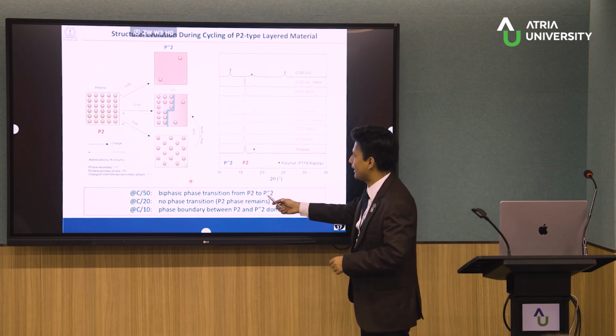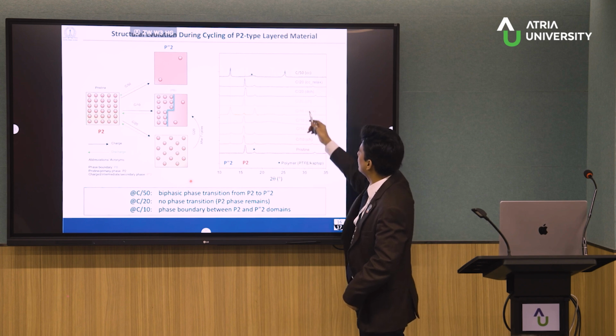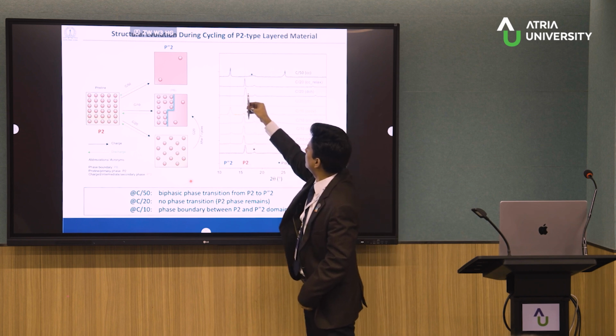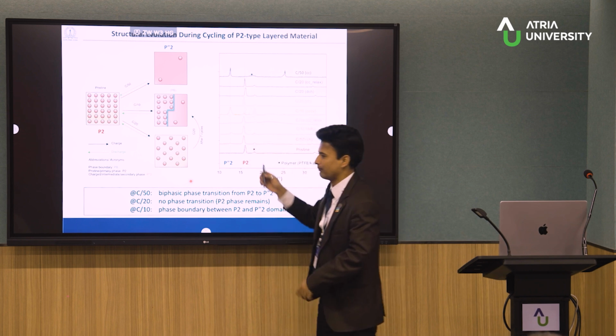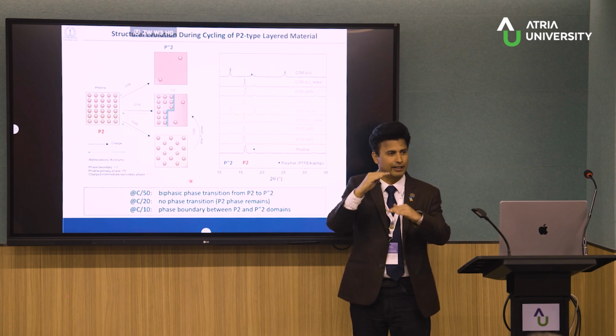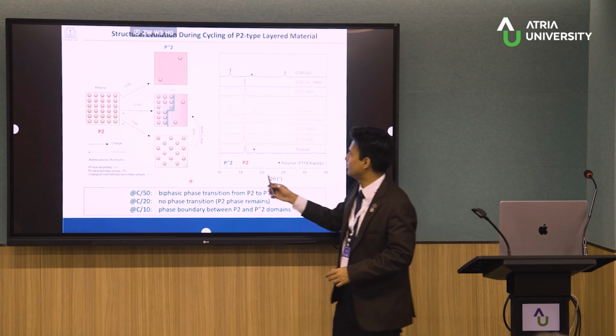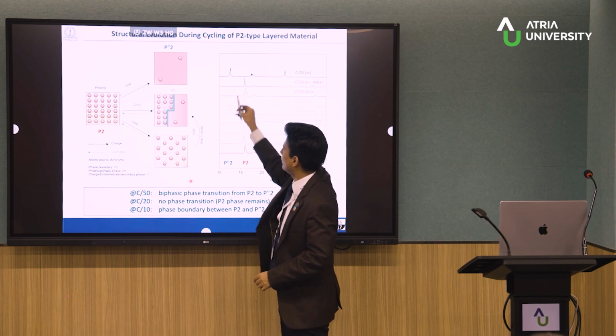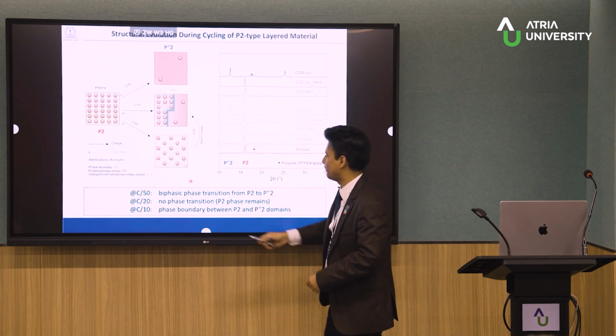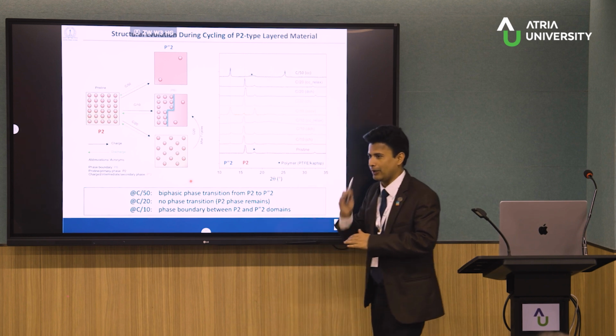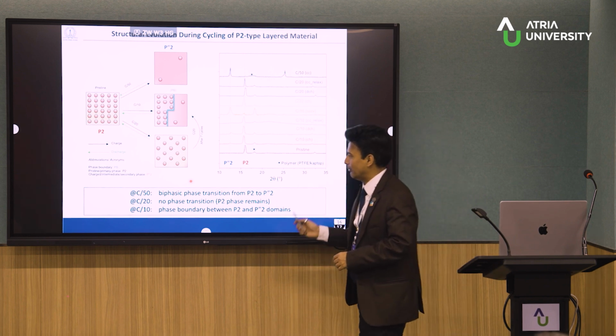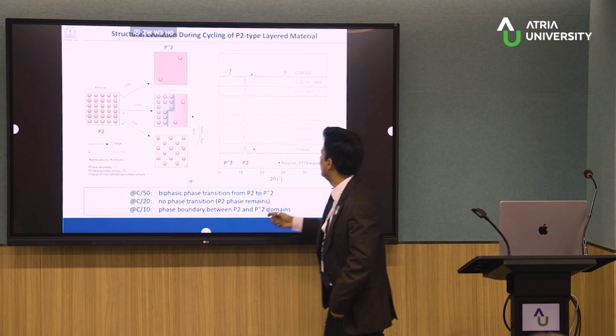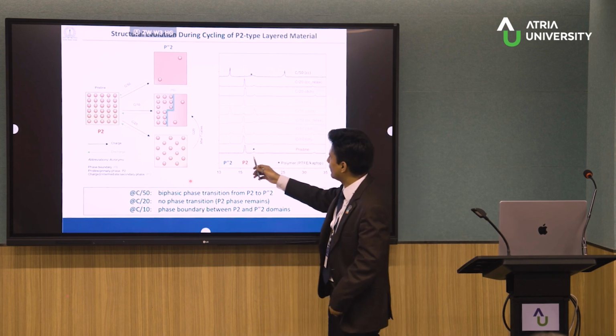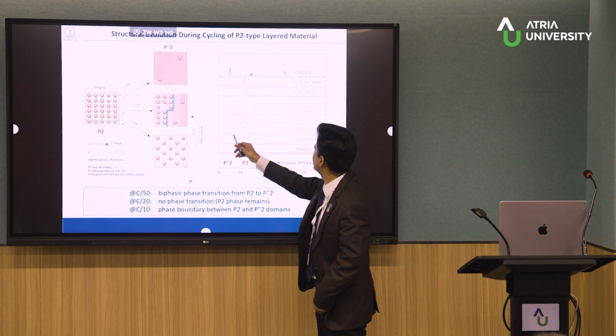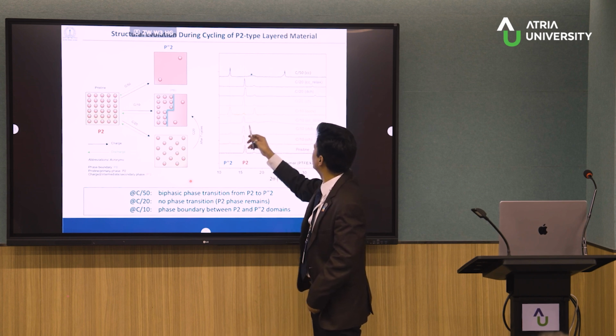Now when we do the same thing at C/20, charge discharge, the P2 remains P2. Just a little bit of change because of the interplanar distance, a slight change, but P2 remains P2, there is no P'2 peak here. So what we feel is at C/20 there is no phase transition, it is a single phase P2 that remains. Now the interesting point is when we do it at C/10, what happens? We observe P2 as well as P'2, you see? P2 and P'2, like that.